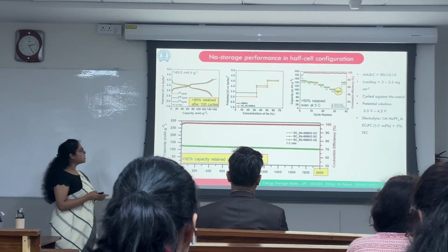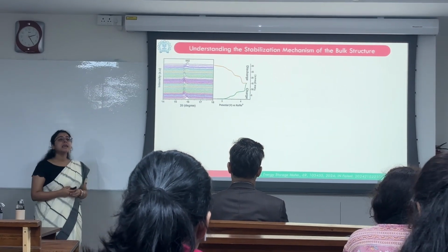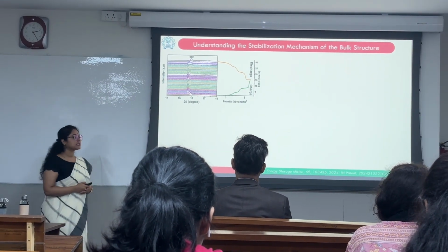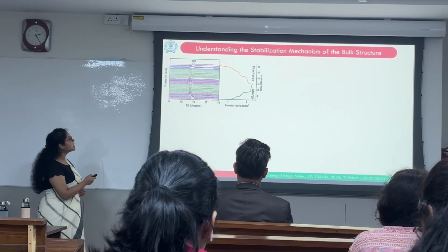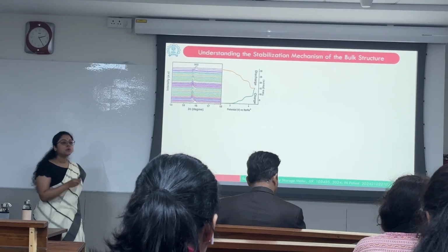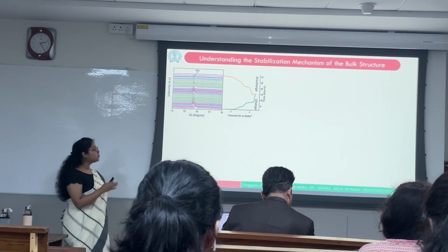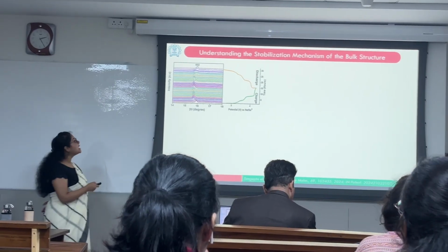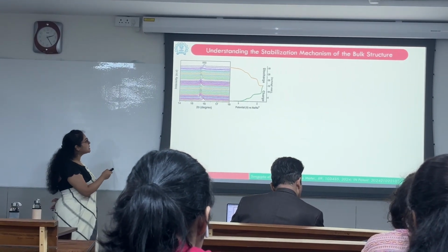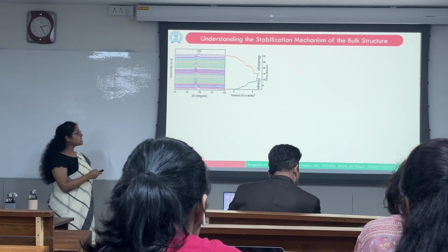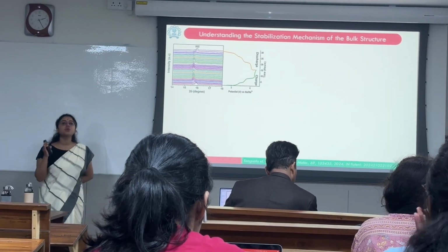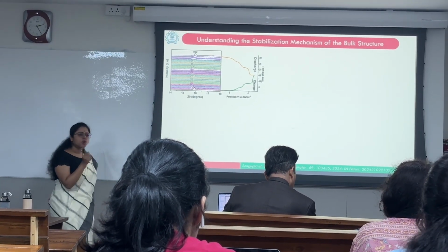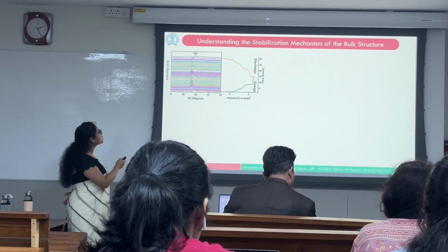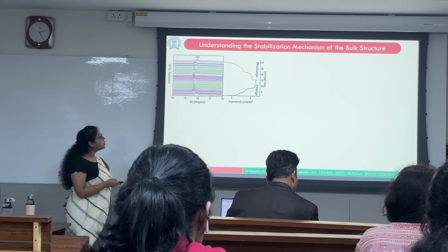However, in order to visualize that, we conducted the in situ X-ray diffraction analysis, which showed that during charging, the 002 plane, which is the main responsible plane for the sodium ion diffusion pathway, shifts towards the lower 2 theta. However, it is to be noted that it doesn't go to the O2 phase, but becomes a distorted P2 phase, which returns back to its original position after fully discharged.